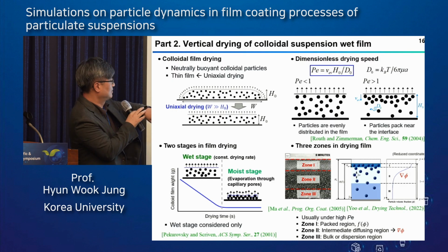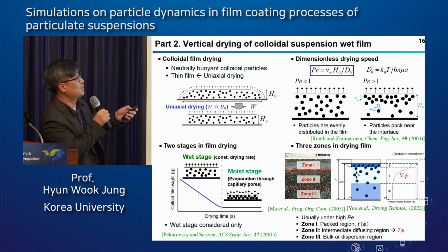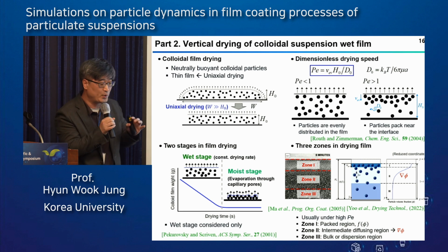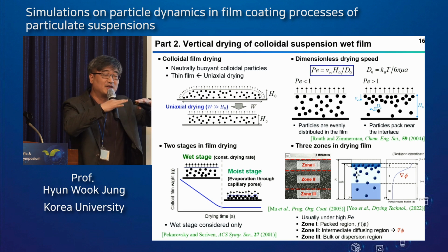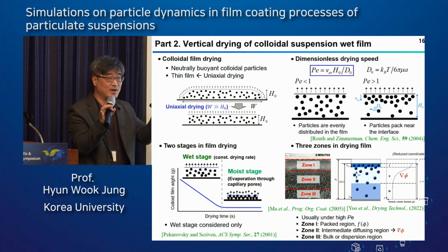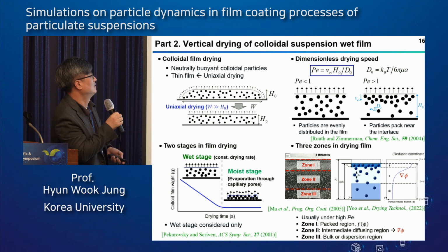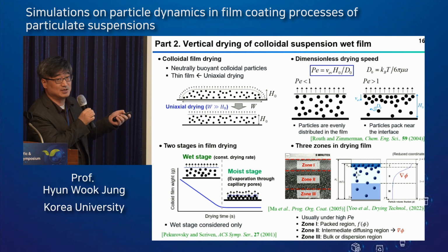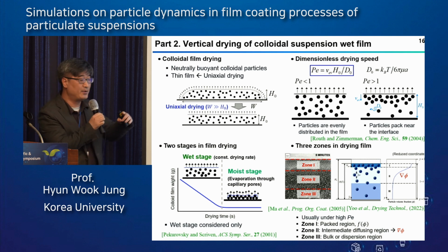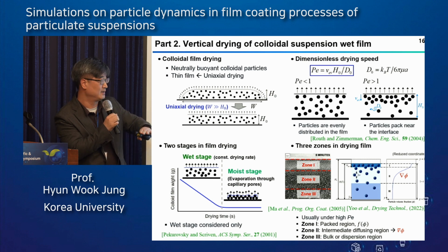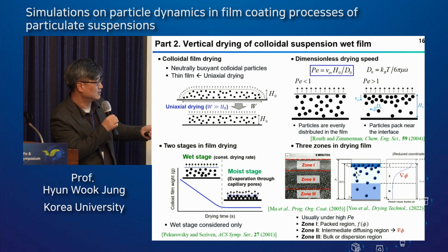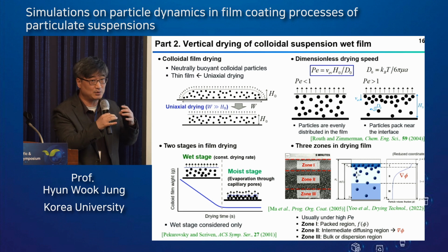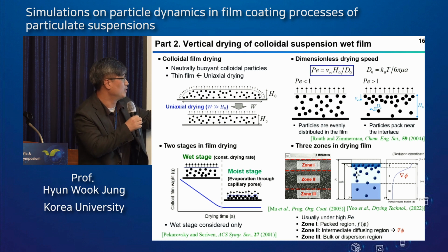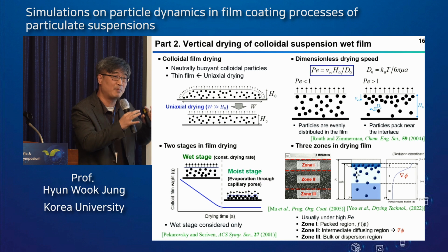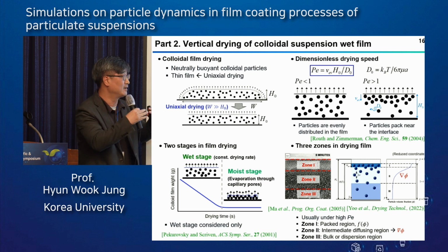So the second part is vertical drying of a colloidal suspension wet film. In this case, we only consider simplified, one-dimensional vertical drying, neglecting the edge side. So there are two drying stages. The first is the wet stage: the air-liquid interface is linearly moving down, as shown here. And the second is the moist stage: just evaporation through the capillary pores without any change of structure. So we'll only consider the wet stage to check the particle dynamics during the drying.